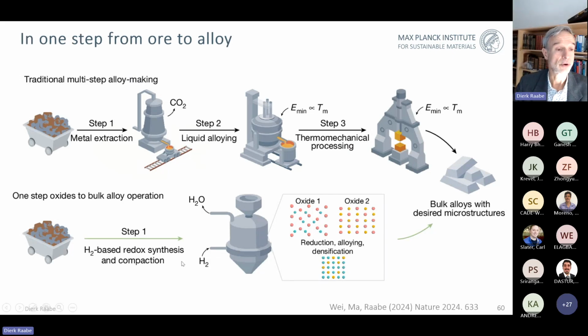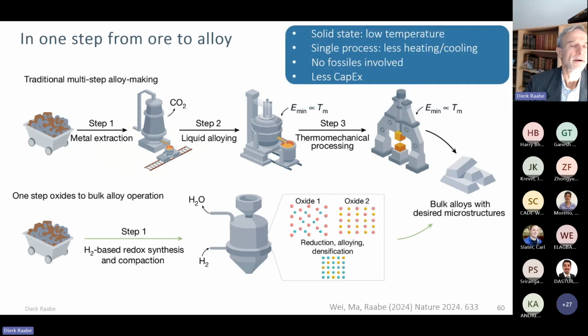And we have now replaced these 3 steps by a single reaction step. Several groups have also looked into this alternative before us. What we have done here is mix several oxides in the appropriate stoichiometric fractions and do the hydrogen-based direct reduction plus the mixing plus the densification and pore closing and so on, and to some extent, depending on the material, also the microstructure design, in one single reactor step. In principle that sounds like a very trivial undertaking, and it brings about a couple of advantages.